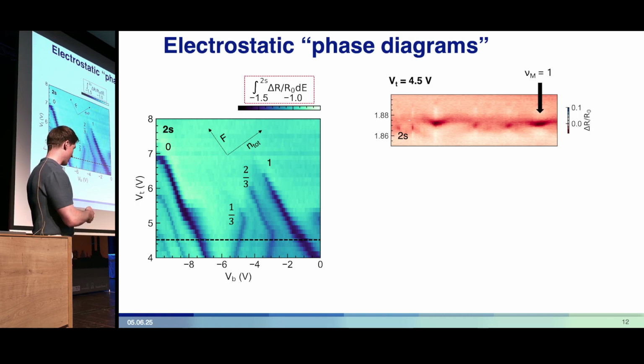From the phase diagram, we can extract the line cut, this black dashed line, and look at what the excitons are doing along that line in parameter space. This is the data I showed before, where we have the nu equals 0 and nu equals 1 insulating states and the generalized Wigner crystals.